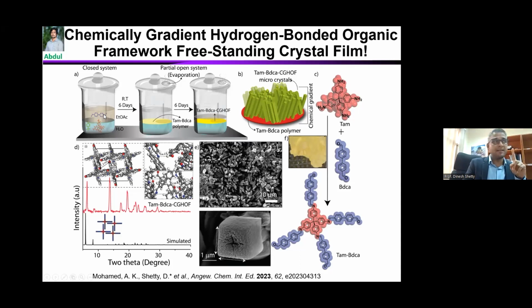But in this case, what we did, we controlled the reaction kinetics by doing open and closed system. Before, we used this interfacial synthesis in an open system completely. In this case, we used a closed system for 6 days, then we opened it a little to make it partially open. The interesting thing that happened here: in the first 6 days, we end up getting an amorphous polymeric film.